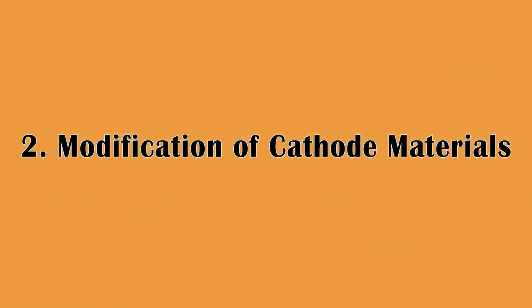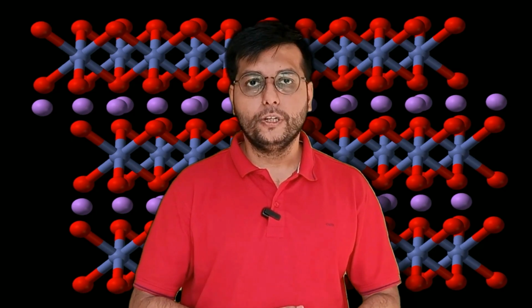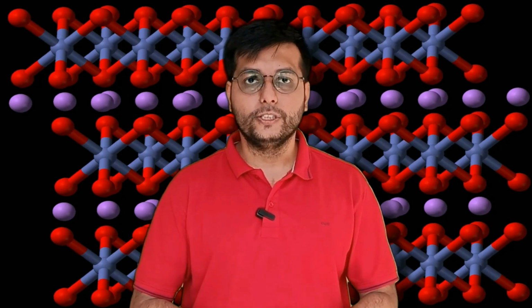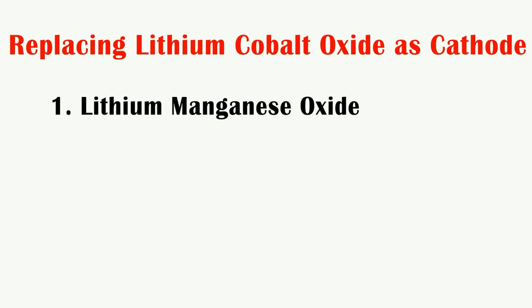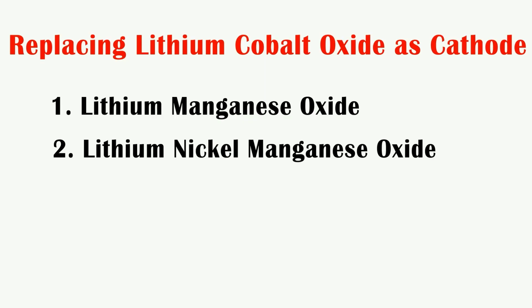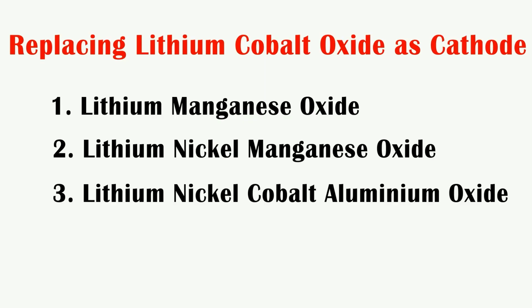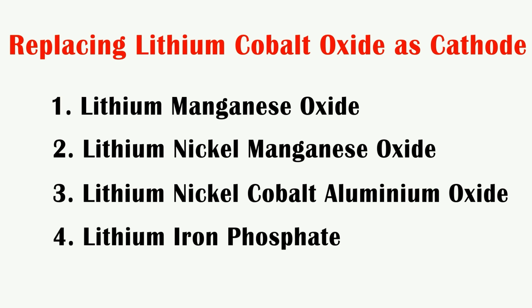Second, modification of the cathode materials. In replacement of the lithium cobalt oxide cathodes, various other lithium metal oxides or lithium metal salts have been deployed to check the thermal stabilities of the lithium-ion batteries, such as lithium manganese oxide, lithium nickel manganese oxide, lithium nickel cobalt aluminum oxide, or lithium iron phosphate.